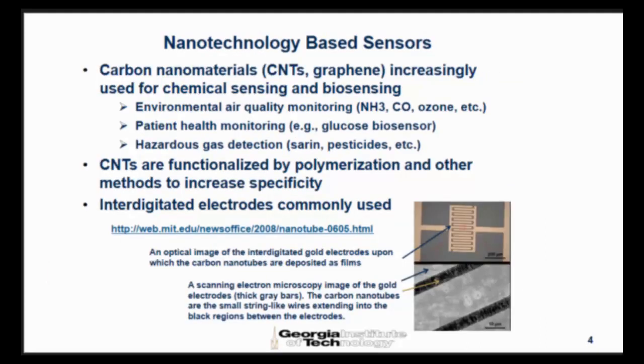This is an example of a sensor from MIT, Professor Strano's group. Basically, it is an interdigitated capacitor on silicon. These are gold electrodes, and you can see in this SEM micrograph that in between these gold electrodes you have nanotubes aligned in the direction of the electric field, perpendicular to the electrodes, and that will maximize the capacitance. So basically this entire area is covered by nanotube films, and that will change the capacitance and give a shift in resonant frequency if this capacitor is part of a resonance circuit.